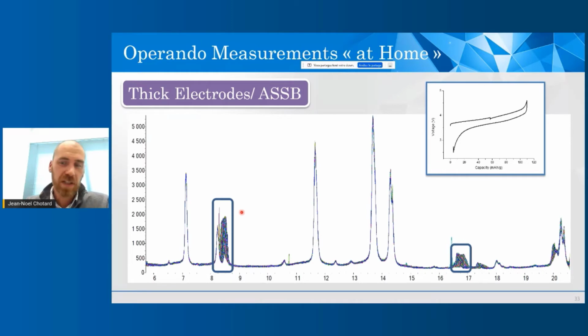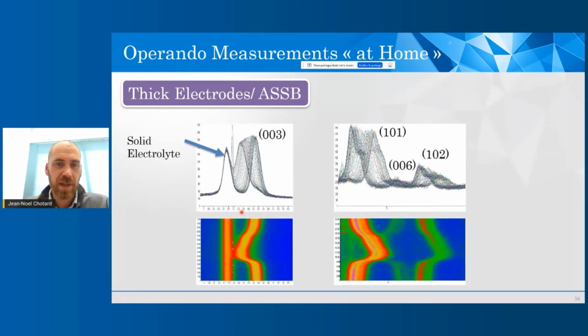But some peaks are moving, and if we look more closely at them, and if we do a contour plot of that, we can here also see the evolution of the cell parameters and of the diffracted peaks. And you notice that the evolution is a bit different from what we can have with regular liquid electrolyte, but it's also because the mechanisms are much different within a solid state battery.